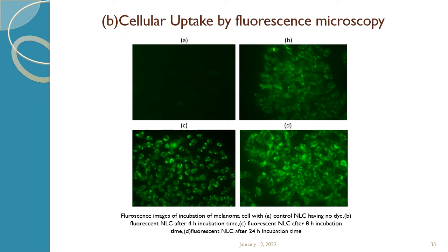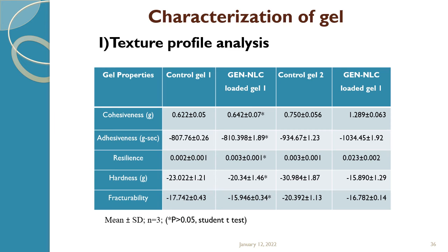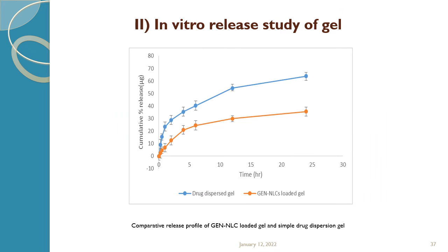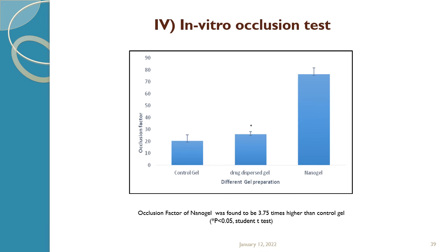The cellular uptake studies showed the retention of these nanoparticles in the skin cells, and the characterization of the gel shows the enhanced occlusivity of this drug. The release studies from the gel also were found to be prolonged. An in vitro occlusion test shows enhanced occlusion of this nanogel.